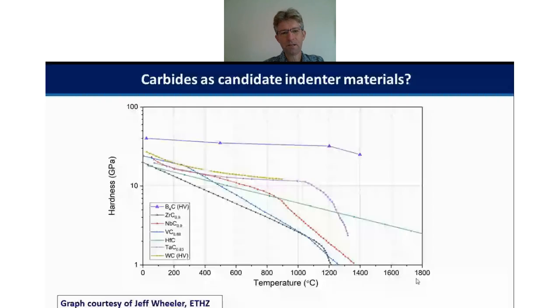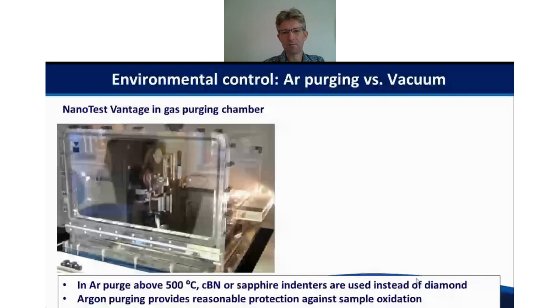And again, these are data taken from non-depth sensing techniques. So these are bulk hardness tests on large samples of bulk material. It's not yet possible to do these tests at these extremely high temperatures over 1200 with nano indentation, but these are bulk hardness tests. And you can see in there, for example, which of these carbides might be useful for further exploring. So boron carbide is particularly promising, but there's not much of it about, so we're looking at other materials.